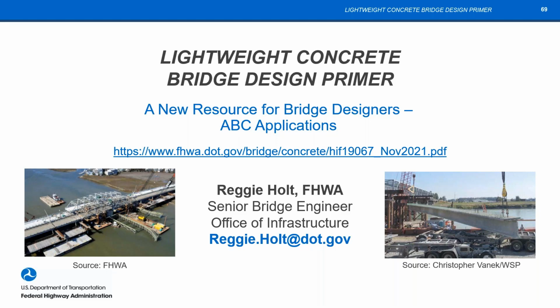There's so much that's involved. Again, it's unexpected. To show me a rock with holes in it and tell me that if you put this in your concrete, you're going to have more durable concrete, or at least equal durability, that's a little hard to believe. But as it turns out, because the pores aren't connected, the aggregate doesn't fill up with water.